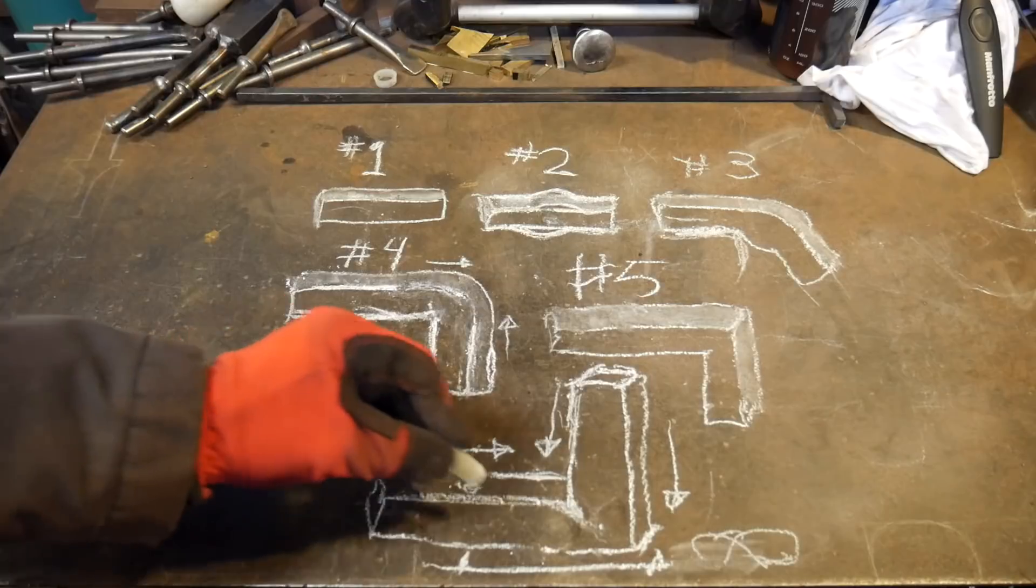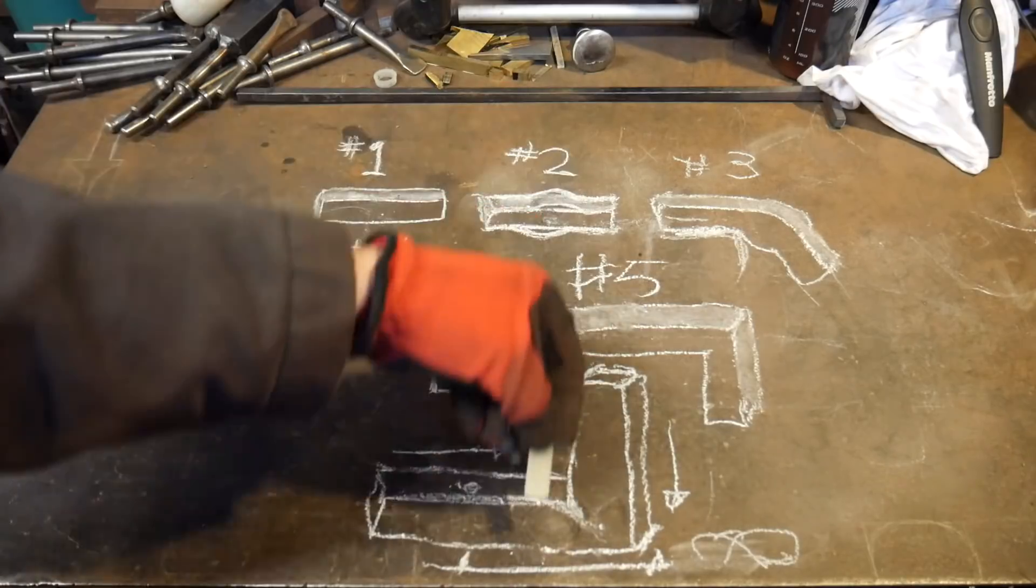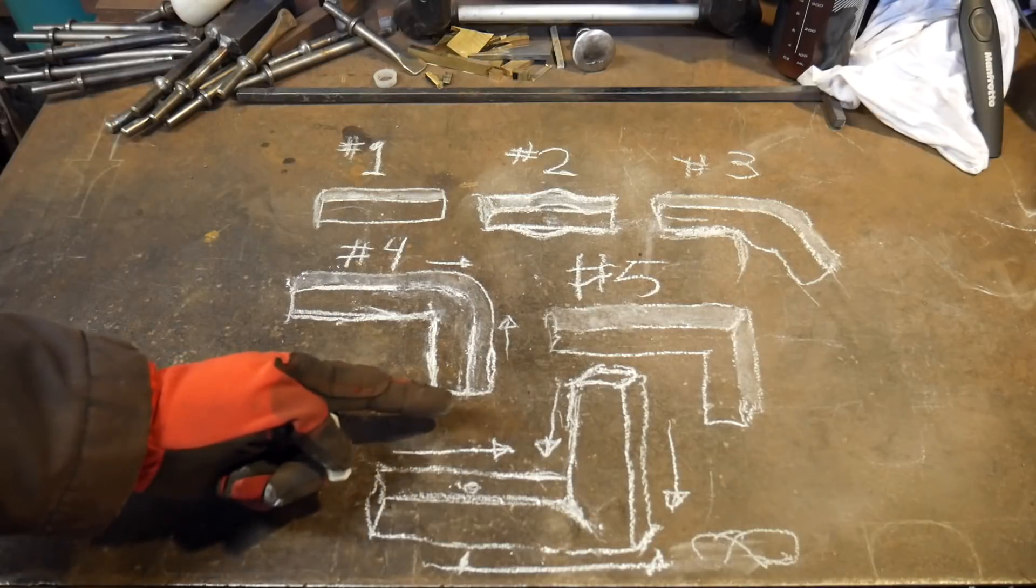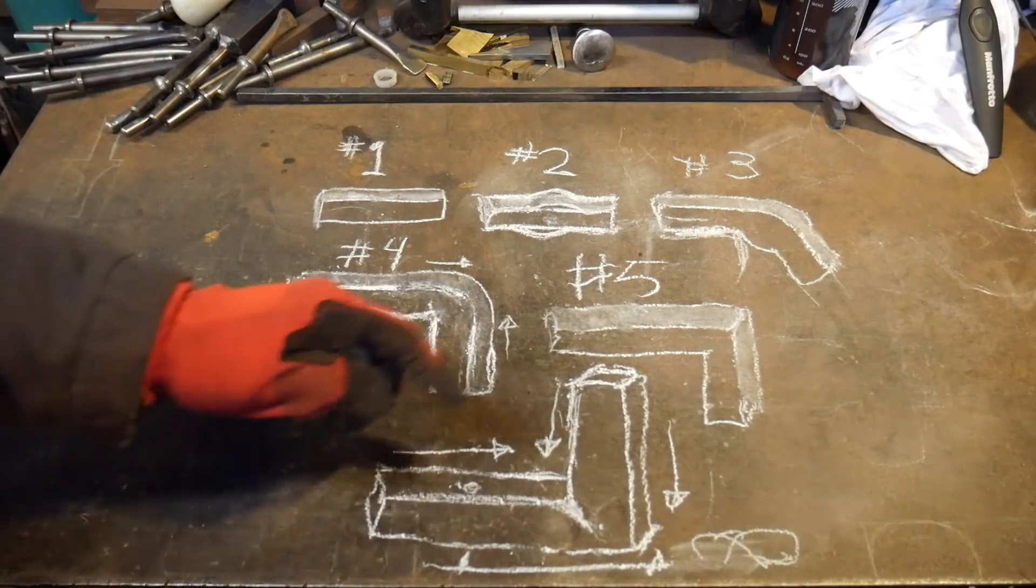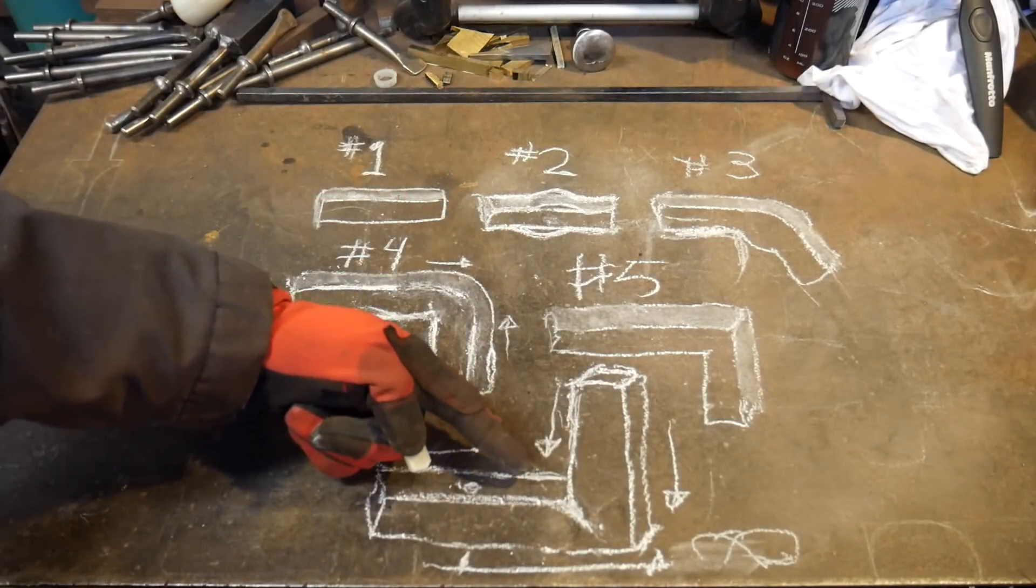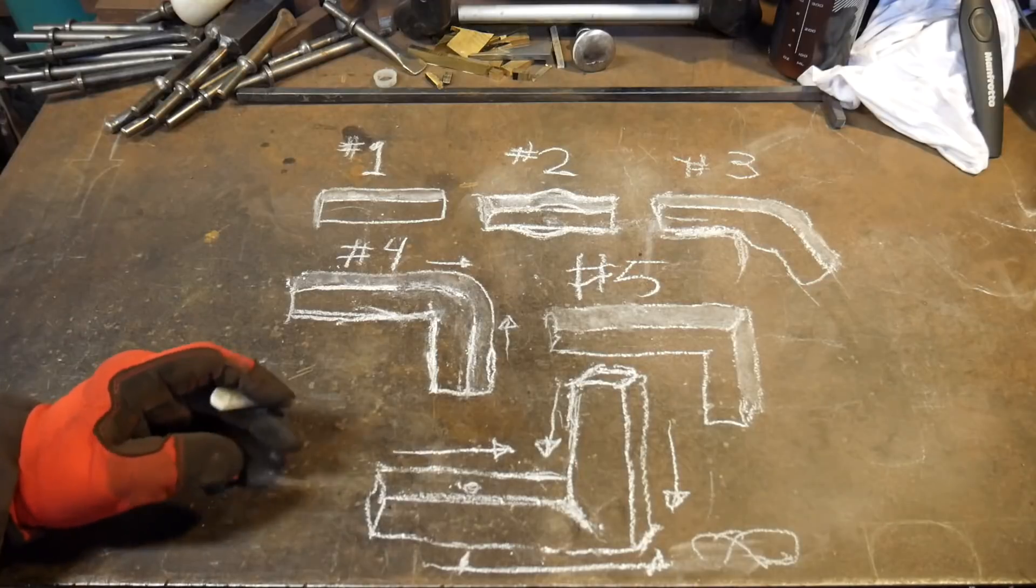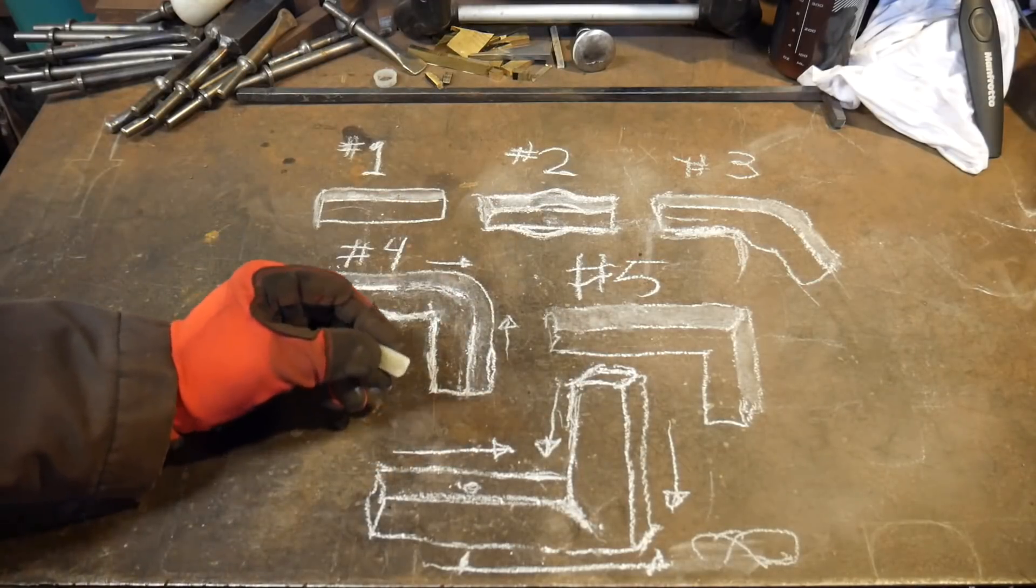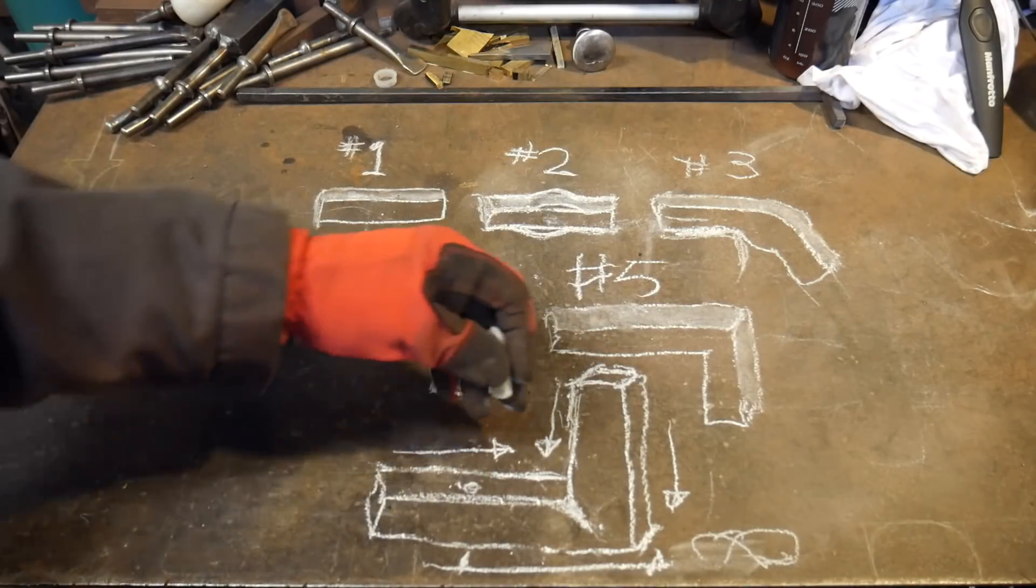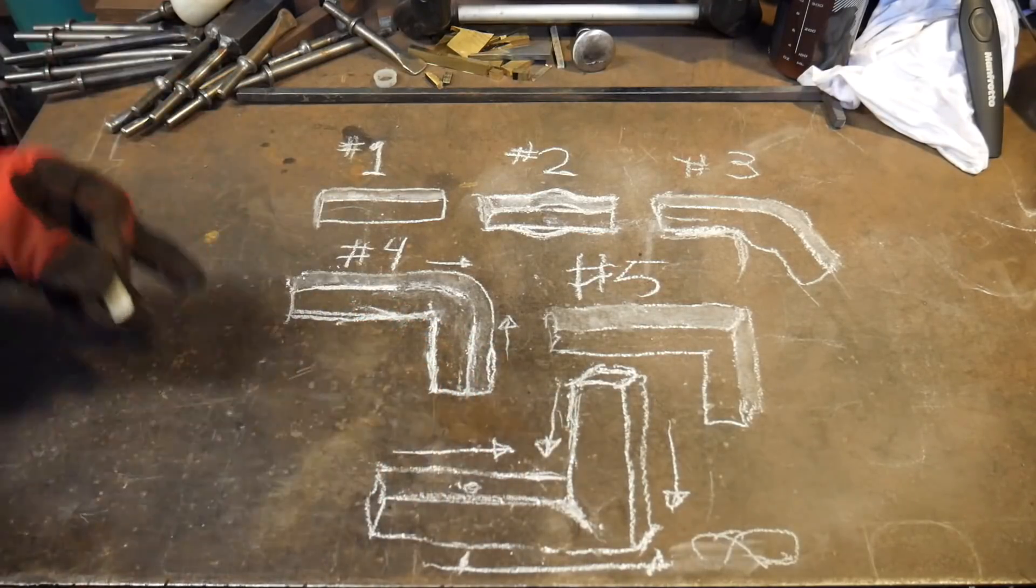Do not fall into the pitfalls of hammering up here and driving this piece down into this piece and create yourself these nice big crack points here. That's the problem with it. That's one problem with doing that method, and you have to be very, very careful. They're very easy to start forming, and there's really only one way of getting them out, and that's to file them out. Once it's to this stage, you pretty much all but lost it, and as long as it's in a decorative piece, I guess it won't matter that much other than looking a little ugly. But if it had to be a mechanical piece, something that formed a function, this is not mechanically stable or sound, I should say.